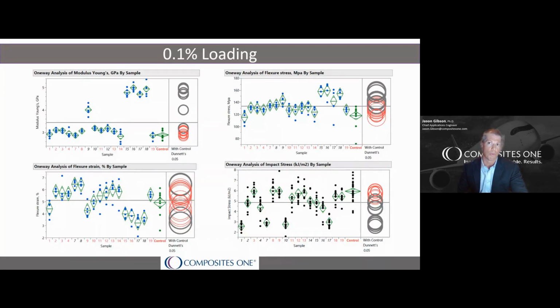So if the circle is shown in red, it simply means that those results are not statistically different from our baseline, and so we consider the difference negligible. But if the circle is in gray, it means that the samples tested had enough of a difference from the baseline that we can be confident that there is a significant change in results, either positive or negative. So if we look at the flexural modulus results in that top left graph, you'll quickly notice the 5 samples I mentioned earlier have a significant improvement over the baseline. And their circles are in gray, reinforcing that they're statistically significant, which is great news.